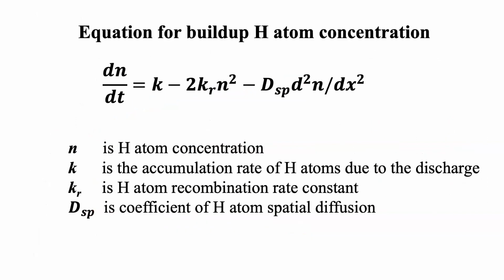How do we analyze it? First, we suggested that the buildup of concentration follows this differential equation. N is the concentration of atoms, K is the rate of creation of this atom due to discharge, this term is the decay of concentration due to recombination of atoms, and this term is the movement by spatial diffusion into the bulk of this sample.